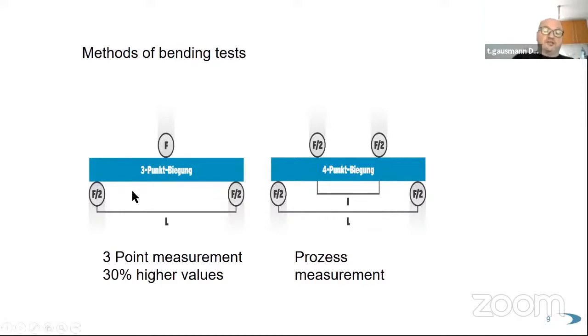A 3-point measurement measures only a very small area. When you've got a blemish, you measure only a very small point directly under the highest force, because here is the highest force, and here you will find any blemish in the specimen and it will break. The better you polish these specimens, the higher the results will be. So this is what I call specimen tuning. This is what we don't do.